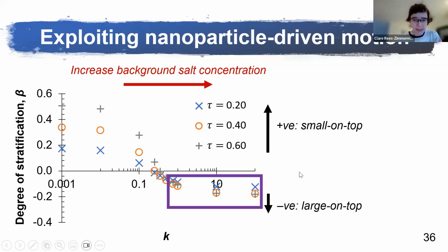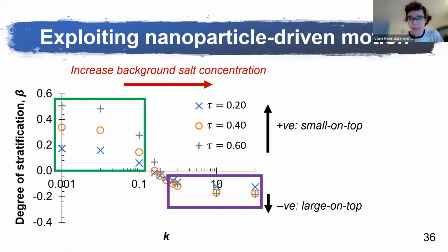And what's interesting is that at large K values, we're getting large on top stratification. Large K values means we've got large background salt concentration, so our electric field is being arrested, and we're pretty much going to get a diffusion-only solution, which is why we're getting large on top stratification predicted here. Then at small magnitudes of background salt, we're having a significant amount of electrolyte-driven diffusiophoresis occurring, and so we're getting small on top stratification predicted. And this plot is suggesting that by tuning the background salt concentration, we may be able to pick our final stratification.